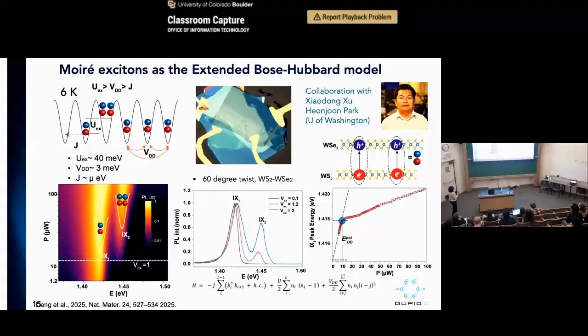So now we know that this repulsive interaction is quite strong, about 40 meV. We then also look at the lowest exciton peak as a function of density, and it also blue shifts slightly. This comes from the second type of exciton interaction, the longer-range dipolar interaction. This longer-range dipolar interaction is weaker than the on-site interaction, but it's still quite strong, on the order of 3 meV. And the tunneling is quite a bit smaller, about a few orders of magnitude smaller.